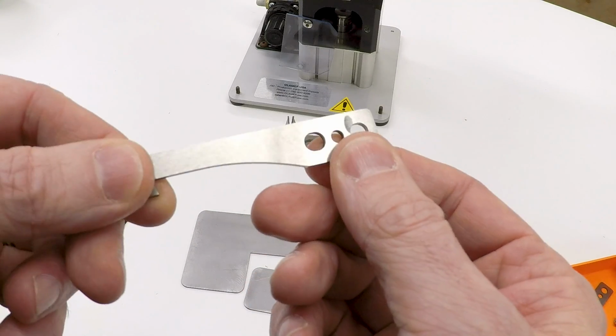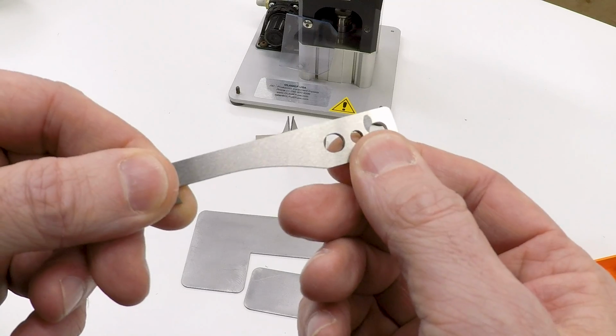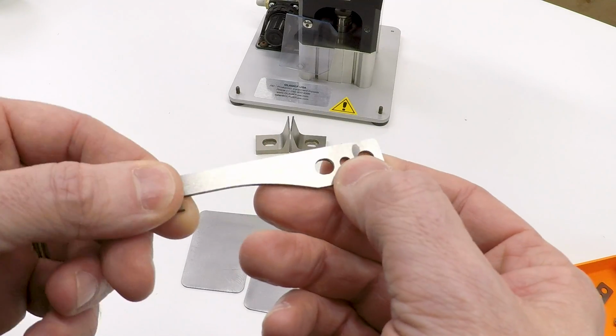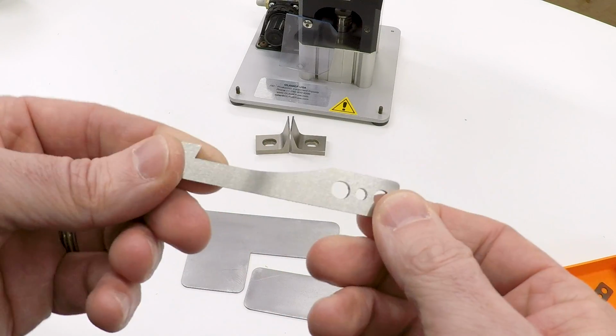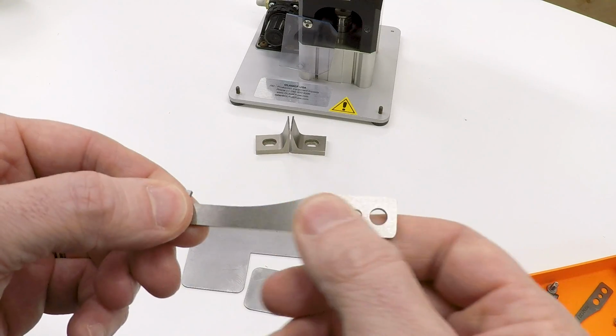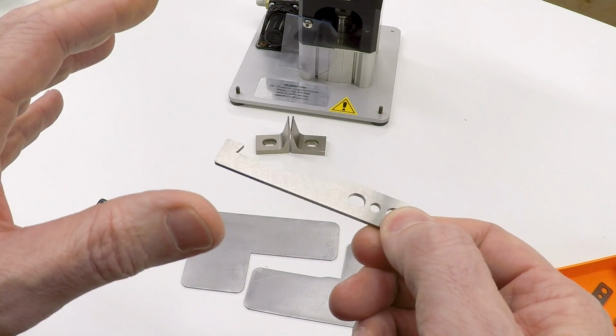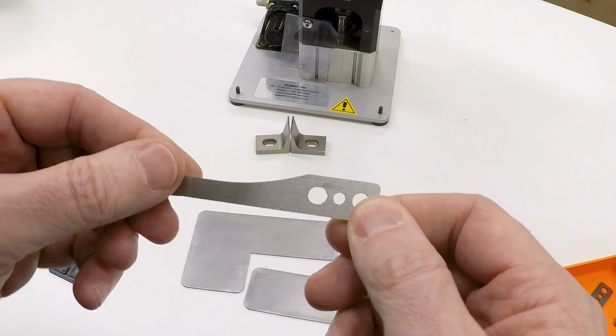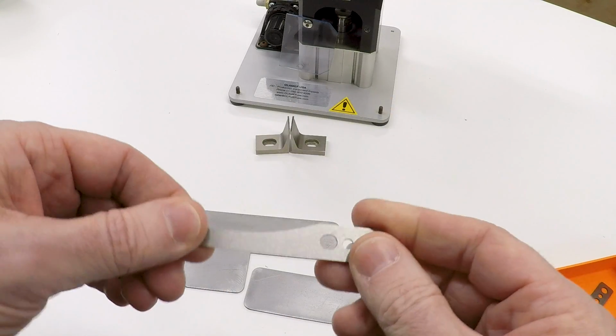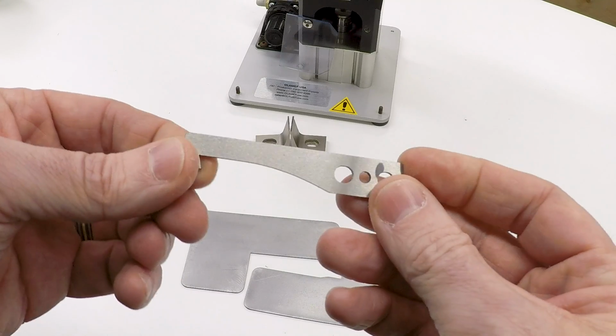And this little beauty mark here is all the evidence that's left over that we couldn't completely grind out without going below thickness for one of those incidents. As long as you keep it moving, it grinds great. We were grinding without coolant with an open structure wheel. The parts were staying nice and cool, but you definitely needed to keep moving.